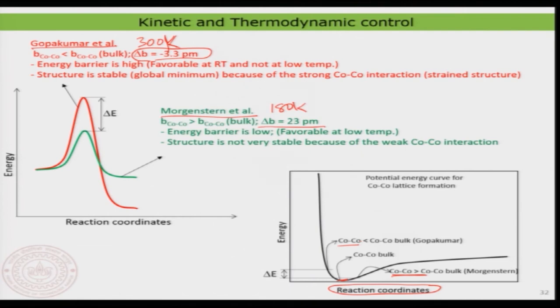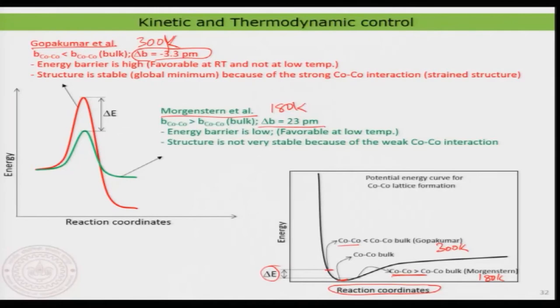So, what happens is that in this case, you would just have a very high energy at the interface, very high energy in terms of the cobalt-cobalt compression, and that is what is represented by this delta E. So, compared to the case of the 180 Kelvin, so this is the case of 180 Kelvin and this is the case of 300 Kelvin, you can see that between them there is a huge energy difference, because the different cobalt-cobalt distances can be seen in the potential energy diagram. So, compared to the equilibrium position, in the 300 case there is higher energy than in the case of the 180 Kelvin. So, the influence is this.